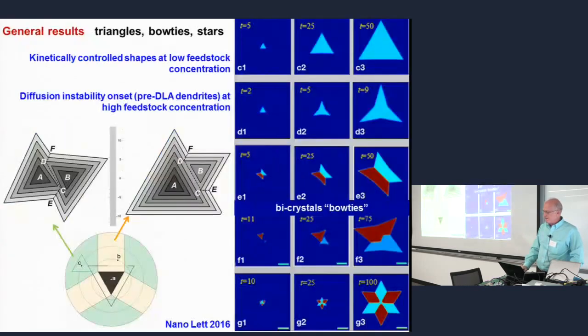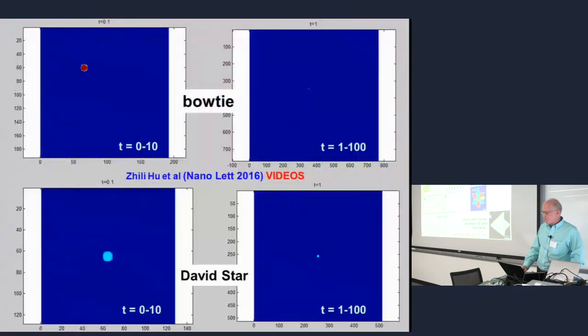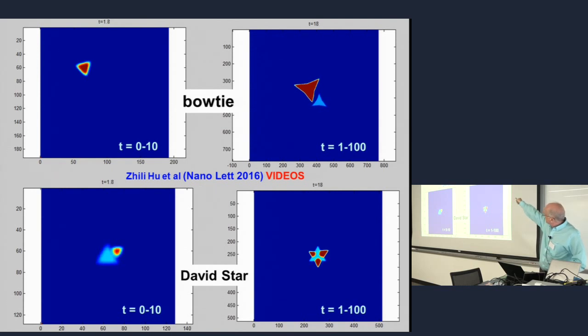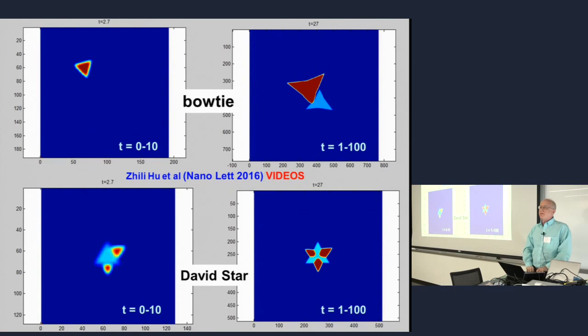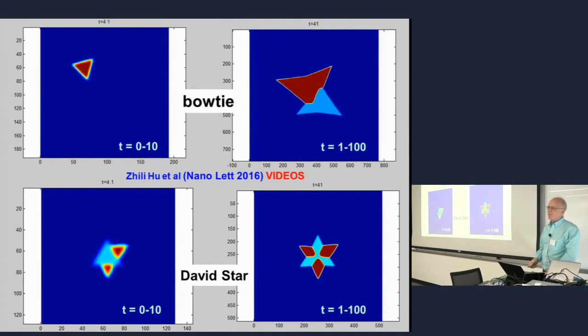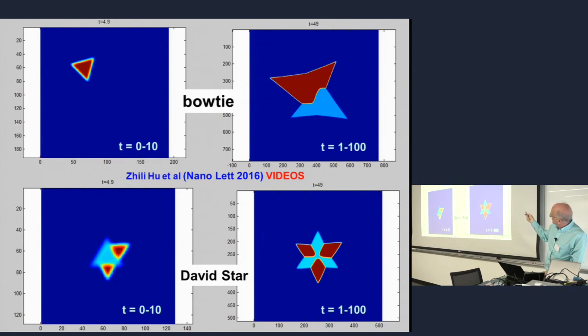And then if you realize that they are twins, then you can ask, so what is the kinetics? How do they form? I will just show you the video because it's a school and it's more entertaining. This is a video, a phase field simulation of how this thing forms, this is a nucleus and this is a second nucleus. So the point is that when they collide, they tend to align to get good contact, and that's where you always get an inversion grain boundary, not an arbitrary angle, but 60 degrees or 180 degrees. And after that they grow, they become a bow tie.